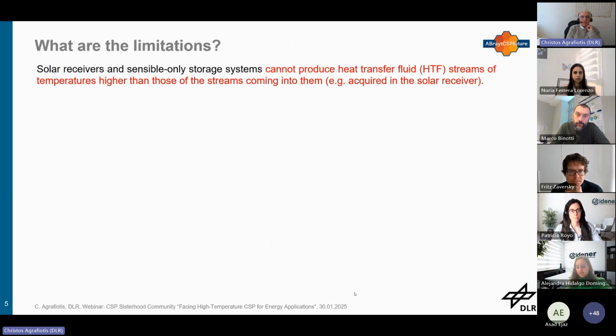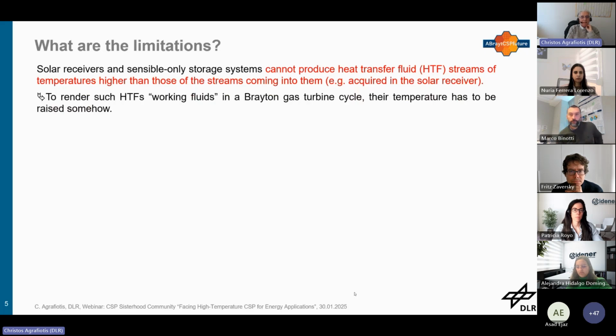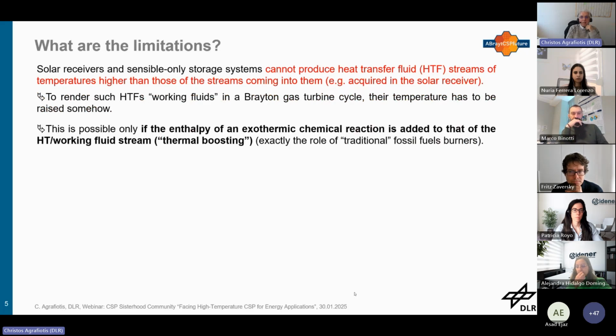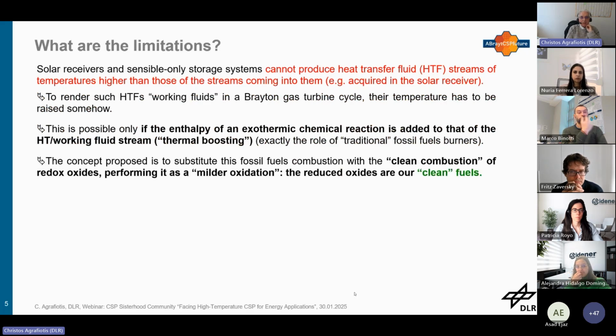The limitation is obviously that one is limited by the receiver. So heat transfer fluids in principle cannot be heated higher than the temperature of the receiver. So in other words, where one wants to use a combined Brayton cycle, this temperature has to be increased. And this is, if you add to this temperature the enthalpy of an exothermic chemical reaction, and that's exactly what happens when you have traditional fossil fuel burners that burn gas and power the gas turbines. This thermal boosting, of course, the idea in this project is, instead of using fossil fuels, to use an exothermic reaction of clean fuels of reduced redox oxides.